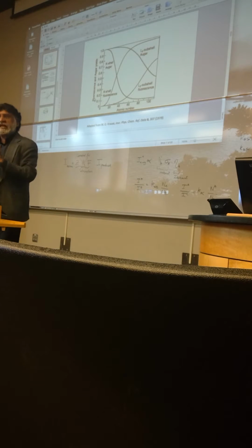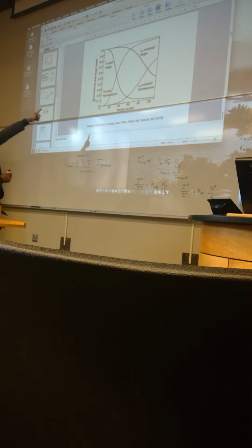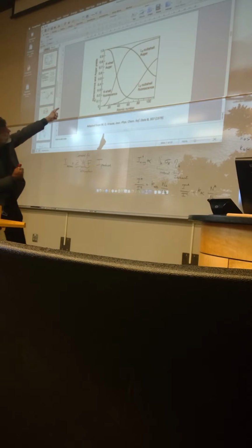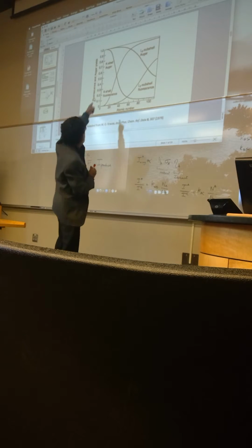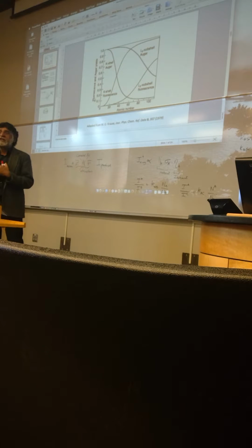It's not necessarily the case, but for the very low atomic number elements, you can really clearly see that it prefers the Auger. It produces some X-rays, but it produces more Auger. All right? So this is a very important plot that tells you that here you have the K shell Auger, fluorescence, L shell, and so on. And as you go to higher atomic numbers, the Auger completely drops off and the X-ray fluorescence, so the X-ray production, really increases.